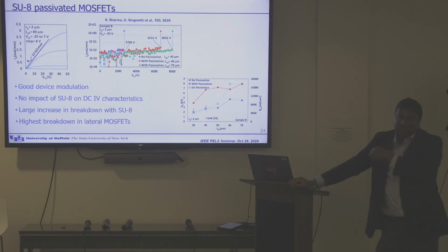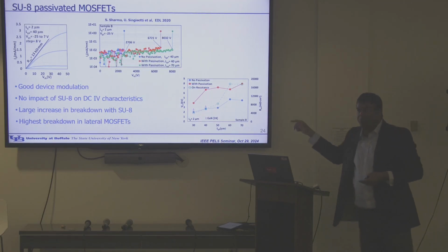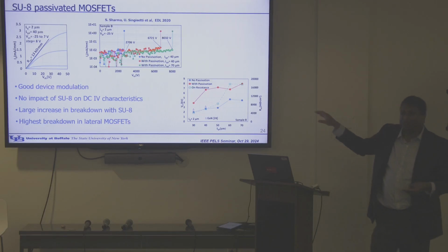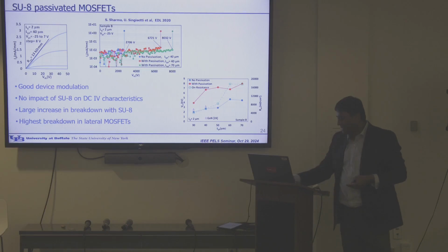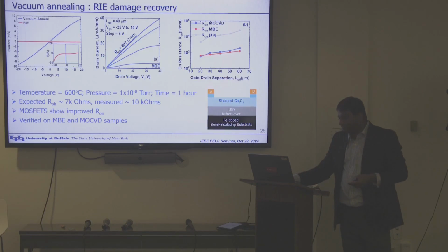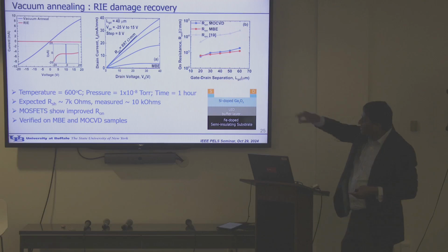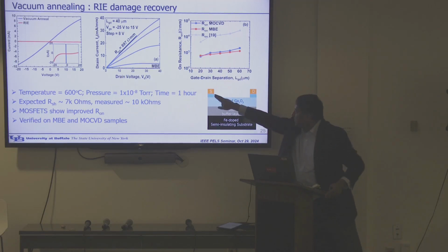And we, in fact, verified this a couple of times in the paper. We have actually 2 devices stored because we were surprised that this is a big enhancement. And in fact, it's true. After this, a lot of groups started using this, even for gallium nitride devices, and they have seen improvements in the breakdown voltage.